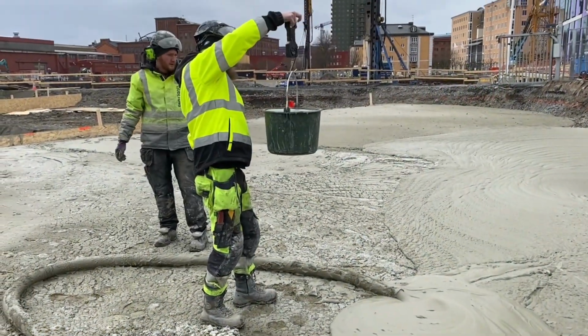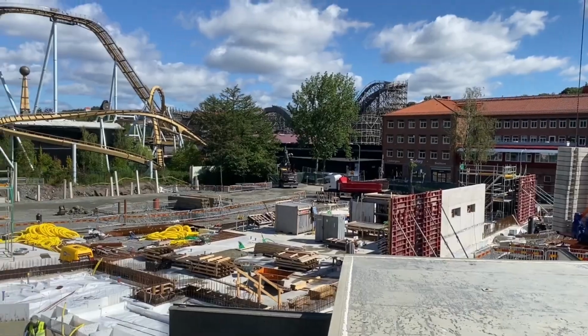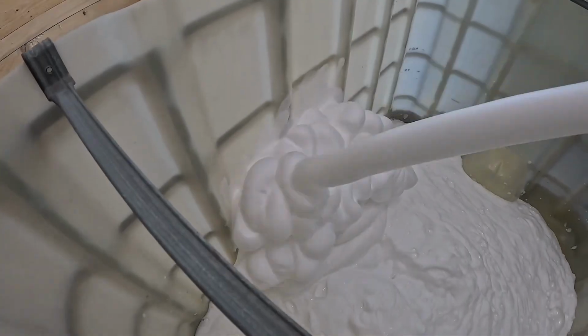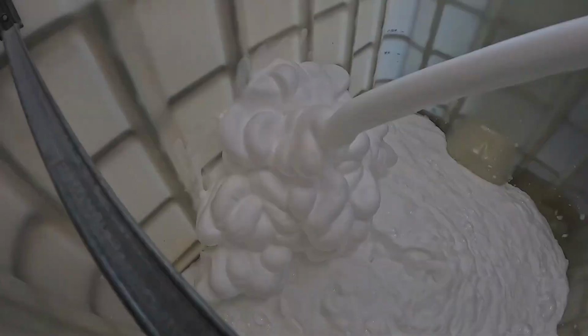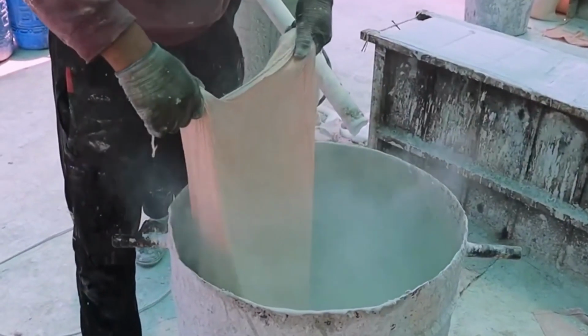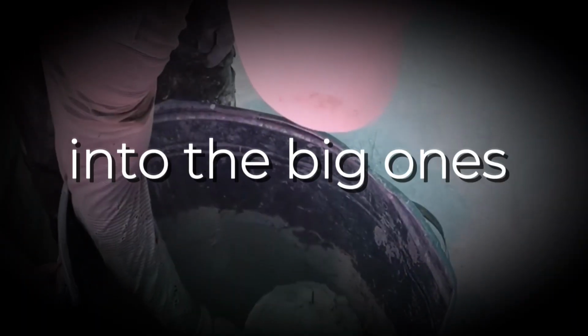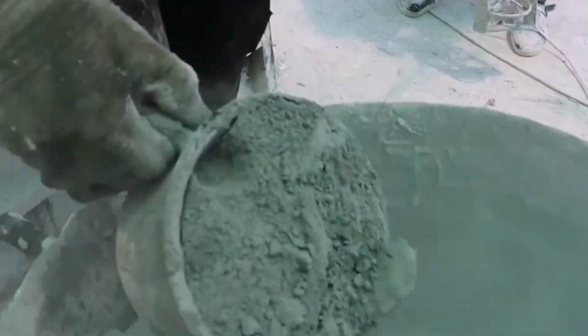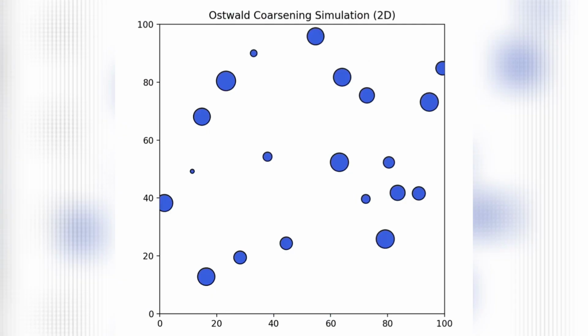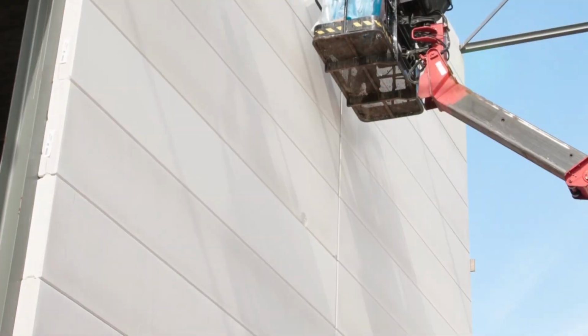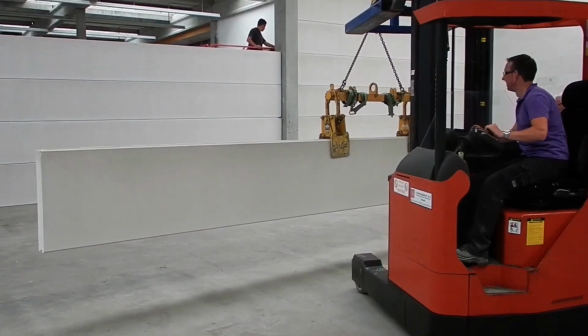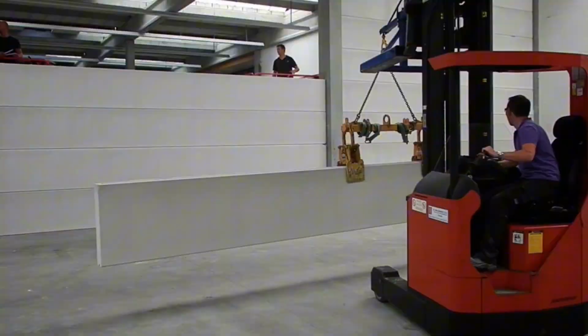The trouble is that a bubble sitting in wet cement is in a hurry to stop being a bubble. Two things go wrong. Bubbles touch and merge into larger bubbles, and gas diffuses straight through the liquid film, from the small ones into the big ones, so the small bubbles shrink and disappear while the large ones swell. Chemists call that second one Ostwald ripening. Either way, the result is identical. The fine, even pore structure you mixed collapses into a coarse, uneven one. Sometimes the foam simply breaks down before the cement has set at all.